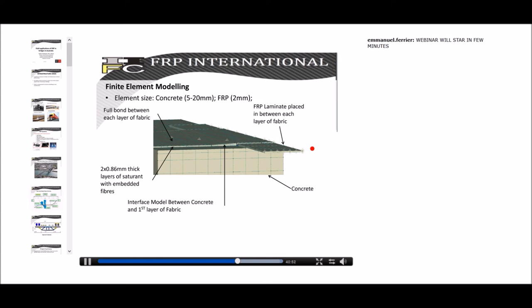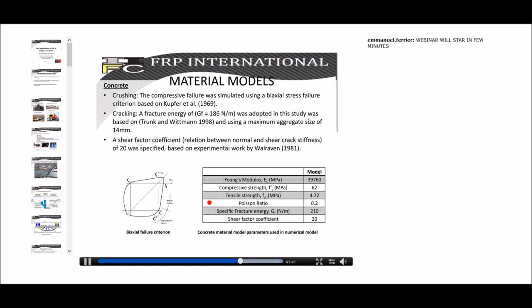We combined our experimental work with extensive, very sophisticated finite element simulation, which took into account every component of this composite, with the layers of the epoxy and the concrete. The model here considered all the sources of material nonlinearity in concrete: crushing, cracking, nonlinear compressive behavior, concrete softening and concrete tension softening and so on. And the same with the adhesives and the bond slip between the carbon fiber, the adhesive and the concrete.